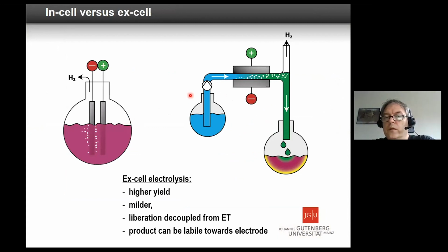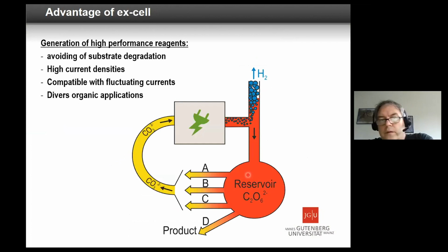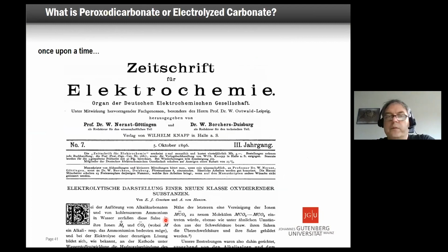The ex-cell version allows you to make a reagent, generate it in a flow cell, separate off the byproduct, and then add it. This is always the way to do it if the substrate is not stable towards the electrodes. And here you can work with much higher yield, milder conditions, and liberation. You just separate the electron transfer from the organic transformation. There's one oxidizer I want to show you. This is peroxydicarbonate, and you can even have a reservoir which allows you to have fluctuating electricity consumption, but still do the organic conversion in a reliable way.